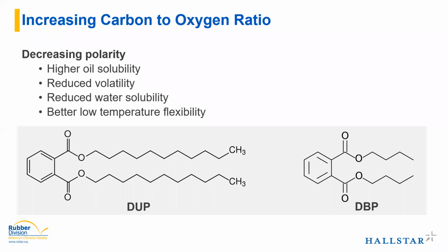So how do we calculate and look at polarity? The first thing we look at in an ester, because oxygen and carbon are the two most common atoms used in an ester plasticizer, is the carbon to oxygen ratio. There will always be oxygens present. That's what an ester is, that group of those two oxygen atoms in the molecule.